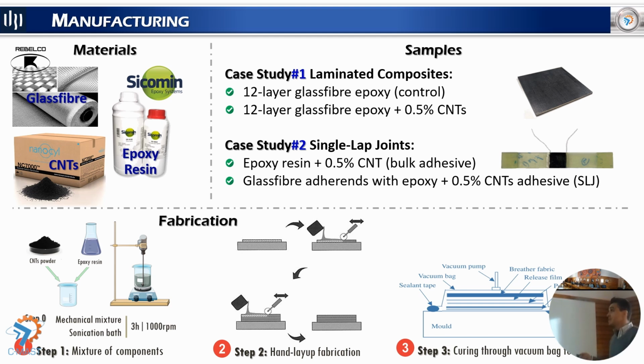For the second case study, we first produced the adhesive we used to bond the adherends. We studied the bulk adhesive with 0.5% of carbon nanotubes, and then we used this adhesive to produce bonded single lap joints with epoxy resin with 0.5% carbon nanotubes, and we used adherends of glass fiber also.